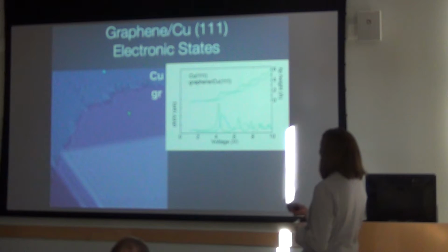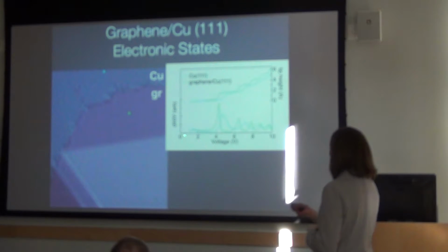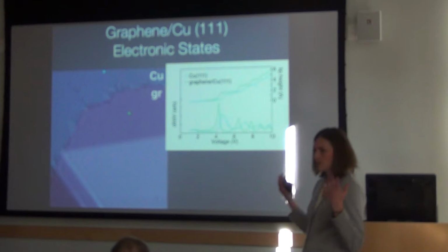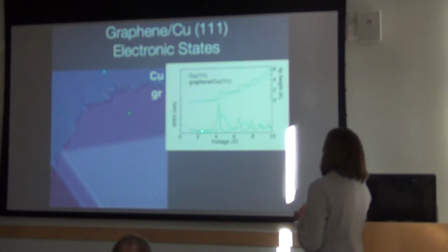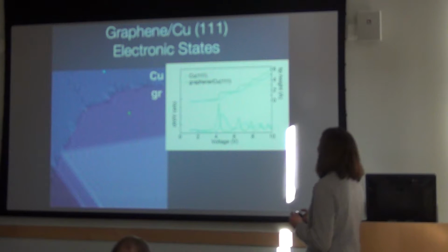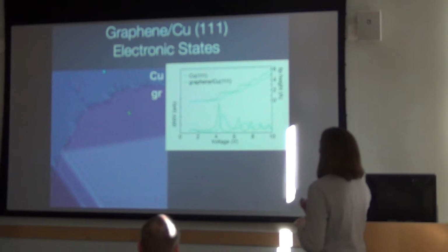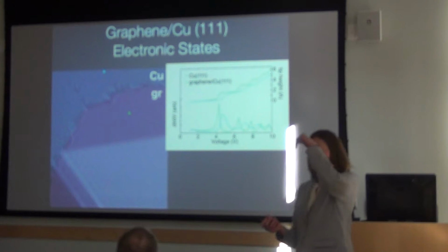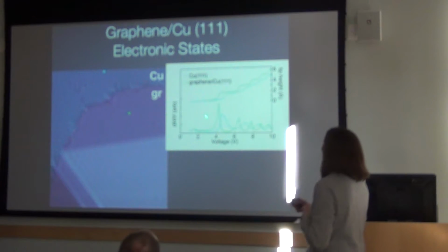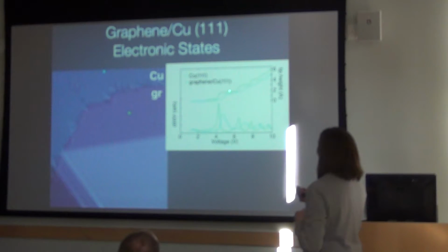Okay, so we look up here and we can compare. So now we have voltages. Before we had voltages from -1 to 1 volt. And now we're at voltages from 1 volt up to 10 volts. And we're looking at these. So the top is the tip height. We do this experiment in a slightly different feedback mode where the tip keeps backing up because the current changes a lot. So this is the tip backing up every time it hits one of these.